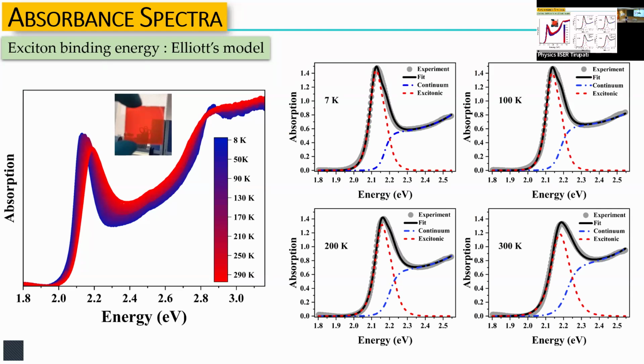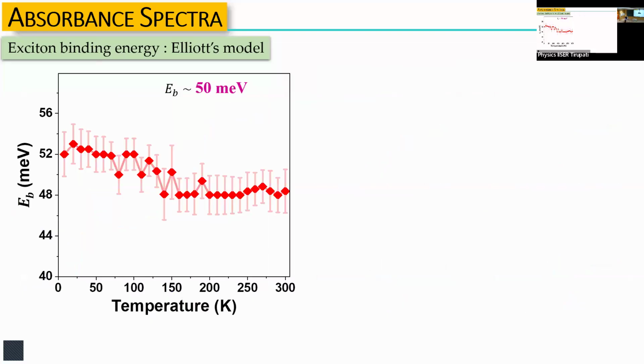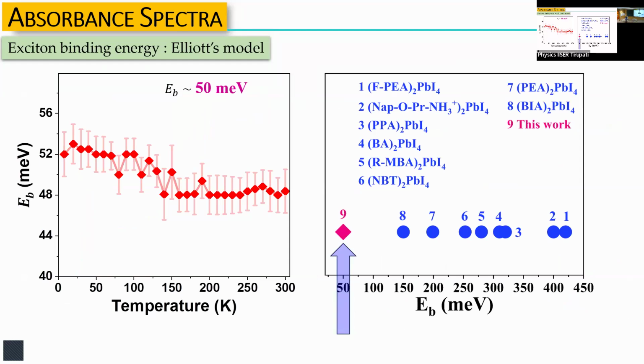There's a rigorous way of estimating it from there. Debashmita did that to find, as a function of temperature, what the exciton binding energy is. But what is relevant is that it is only about 48 milli-electron volt at room temperature. Compared to other materials in this class, it's much lower. Once again, it is so much lower simply because the band gaps are much larger. That gives screening, and also the molecule that she had chosen was chosen to provide very good screening so that the Coulomb interaction gets screened and lowers the binding energy. And she indeed was able to do that.